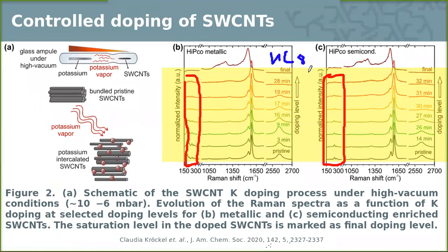KC8 phase. So we know that below that, as long as we still see the 2D line, then we are at something like KC36. Then when we don't see the 2D line any longer, that was one of the very first questions, then we are in KC24.